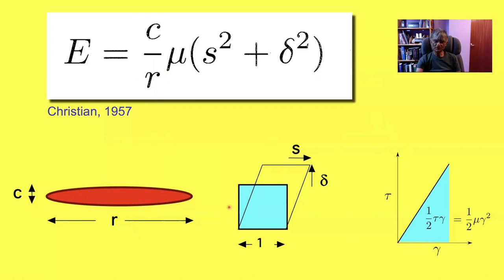So if you focus on this diagram here, the displacement vector is this. The magnitude of the displacement, as opposed to the strain, increases as I move away from the habit plane, because look here, the displacement vector is actually quite small. It becomes larger and larger as I move away from the habit plane. The strain is actually the displacement divided by the height, so that remains constant. But the magnitude of the amount the martensite is pushing against the surroundings increases as you go away from the habit plane.